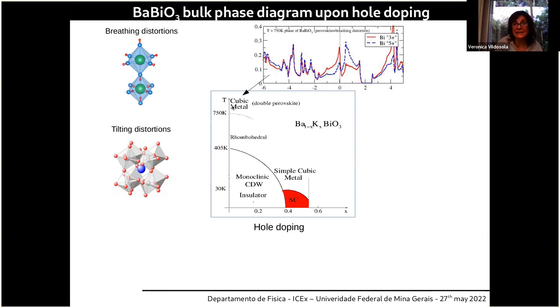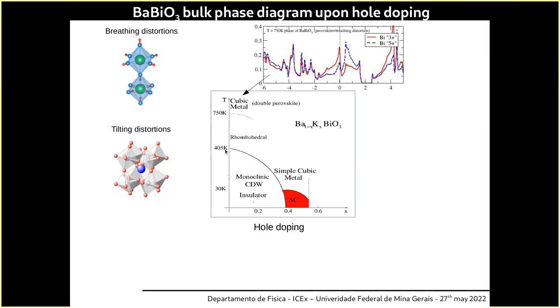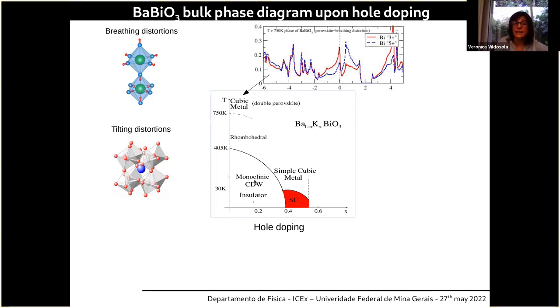But already at high temperatures, we have some valence skipping behavior that makes the system have some charge disproportionation. When the temperature lowers, the structural distortions of the system start to increase. The system suffers first a structural distortion to a rhombohedral structure, and then below 400 Kelvin, the system finally turns monoclinic, charge ordered, and insulator.